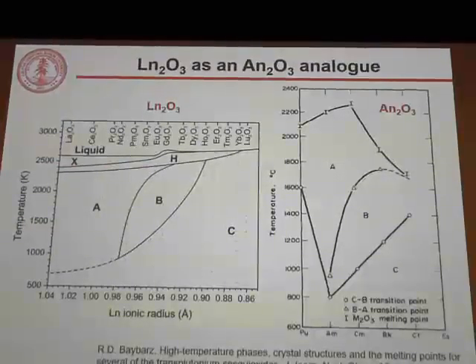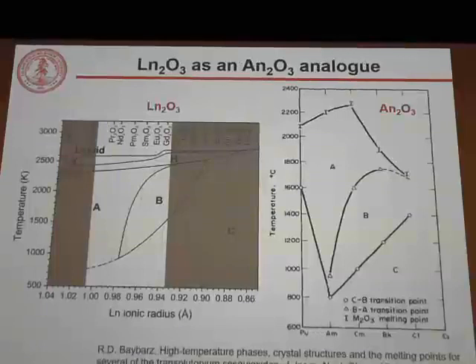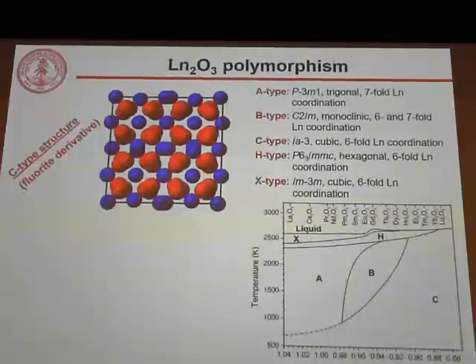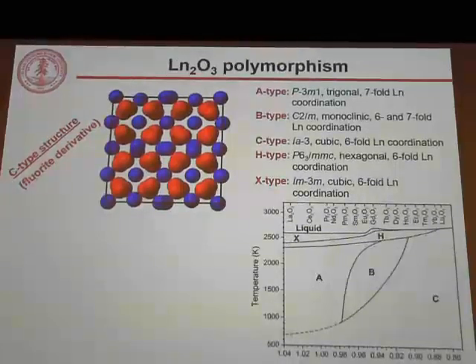So the first research I'll talk about here is on the lanthanide sesquioxide system, which is nice for a few reasons. First of all, its high temperature polymorphism, which I show here, shows that it's a nice analog for the actinide sesquioxides, especially if we look at the same ionic radius range in both materials. So we see similar A, B, C type polymorphism in these materials. Polymorphism is also something we like in this system because we have access to a lot of different phases. So if we're interested in using extreme environments to get specific phase transformations, to access the phases that we might not be able to in the absence of extreme environment processing, this is a great model system to look at.